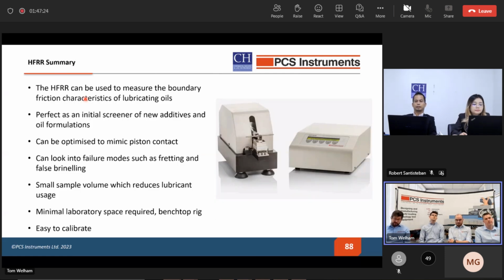So in summary, the HFRR is a standard for diesel lubricity, but it's also a great screening test for lubricant properties, for material, for coatings. It's very quick and easy to use, requires a very small amount of lubricant in order to set the test up. And it can be optimized to look at piston contacts, but also looking at other failure modes such as fretting and false brinelling, which is found in gears and bearings. It takes minimal lab space and is one of the easiest instruments really you can use for this kind of application.